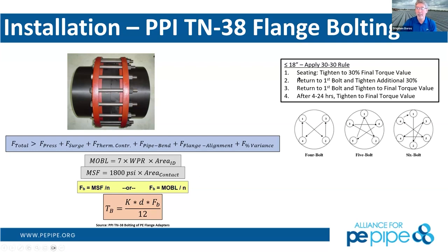So this is just an example. If you're doing less than 18-inch pipe, you do the 30-30 rule. You're going to tighten it to 30% of the recommended torque value. That's to seat it all. Then you're going to start with the star pattern. You're going to go to the first bolt and tighten an additional 30. Go around to all the bolts and do that. Then you're going to go back to bolt 1 and tighten it to the rest of the value. Now, the last step is you're going to let that sit for 4 to 24 hours for it to relax and get in its final state. And then you're going to come back and do one more final torque to that torque value again to fully seat everything and make sure that you have a nice tight joint.